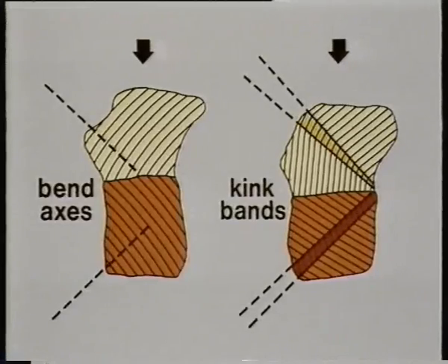In fact, the positioning of the kink band will also depend on what is happening in neighbouring grains and along grain boundaries, and hence is capable of moving through a given grain. In other words, the kink band may be unstable.